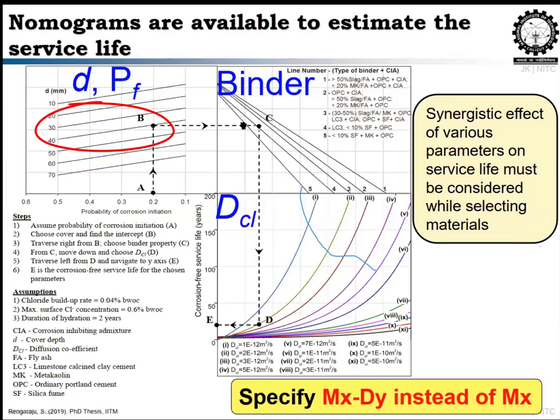So now the management, that is at the B point. With this input, the management team has to choose what material is available nearby. I have given 5 cases here, with some greater than 50% slag or fly ash, which have OPC and corrosion inhibiting nature. And if you see the 5th case, which is less than 10% silica fume and 10% metakaolin and OPC. So like that, 5 cases are there. In your case, you will be choosing which material you want to take.